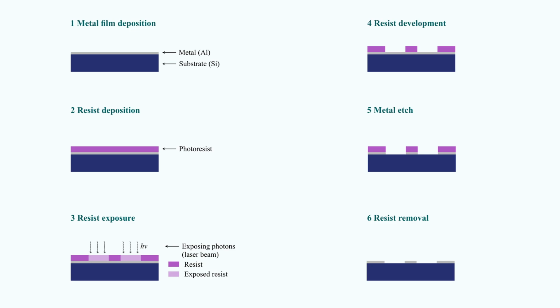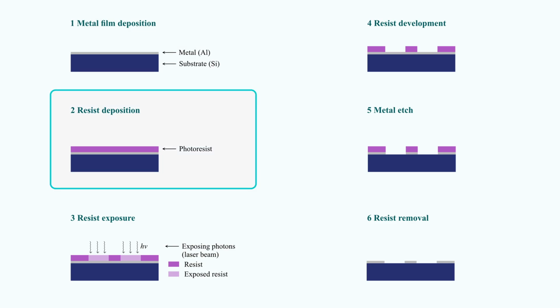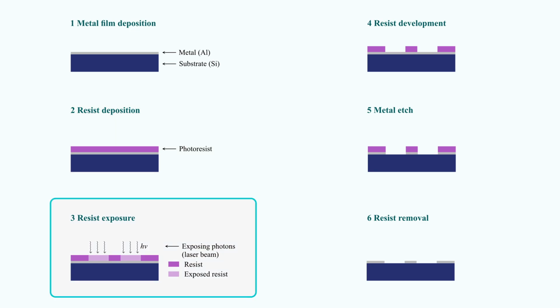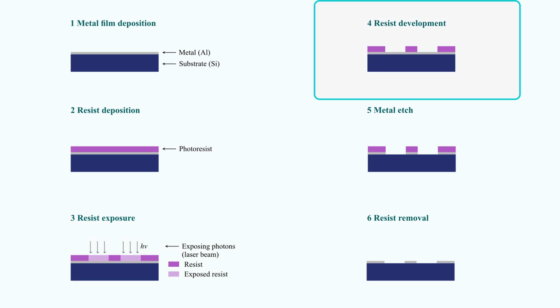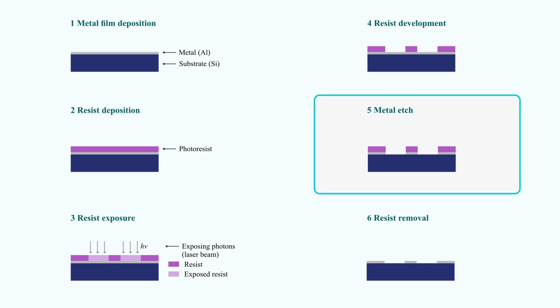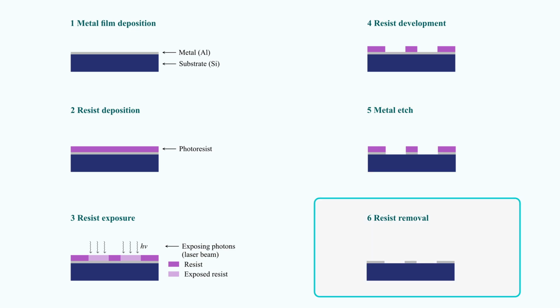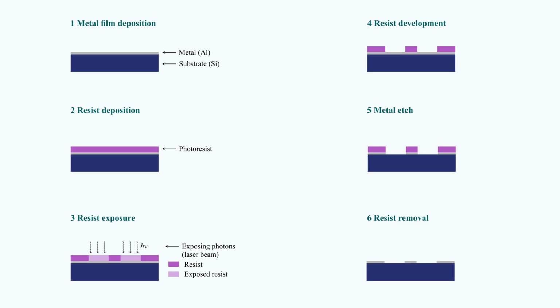To just quickly summarize all of this before we move on. To pattern our aluminium with the desired circuit elements, we will first cover the wafer with a photosensitive resist. Then we will expose our pattern into the resist with a laser beam. We'll develop the exposed pattern, after which we'll get a patterned resist layer on top of a still continuous layer of metal. And finally, we will etch this pattern into the metal using a corrosive acid. After this, we will no longer need the resist layer and can simply dissolve it in, for example, acetone. So that's the version of the photolithography process we will use in this patterning step. Now let's head out to the clean room and get started with the resist deposition.